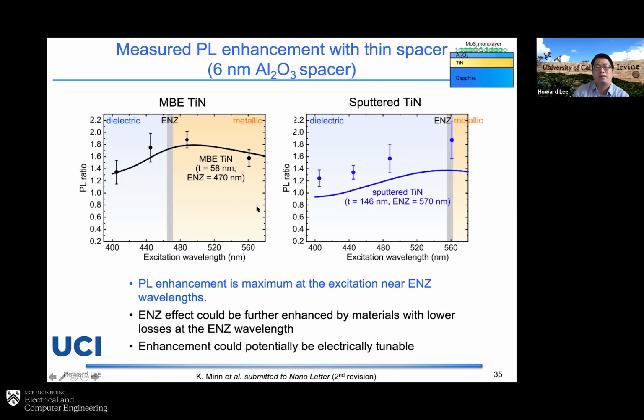And what we find, basically, around this ENZ wavelength, you have a stronger excitation enhancement and a stronger absorption, so it can absorb the light in the monolayer. That's why you have a stronger enhancement near the ENZ wavelength. And again, the lower the losses, you actually have a higher enhancement here, for example, compared to the MBE titanium nitride and sputter titanium nitride. So this is some of the interesting observation. You can really enhance the PL by using ENZ material. At the same time, the losses will play a quite key role here.